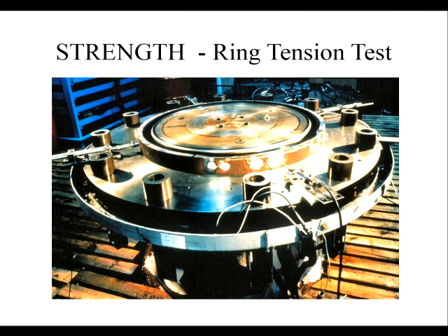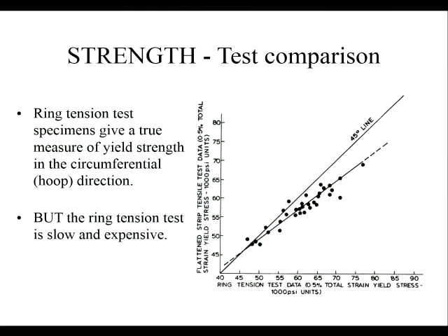And what, of course, people have done is that they've compared the two to give you an idea of what you would expect. So we've got ring tension test data at the bottom, and we've got flattened strip tests from the same materials at the top, and these are the different data points that we've got for different grades of steel. You can see going from X50 up to 85 or something like that. And if there was a perfect match, if they gave exactly the same results, then all the data would fall on that 45-degree line.